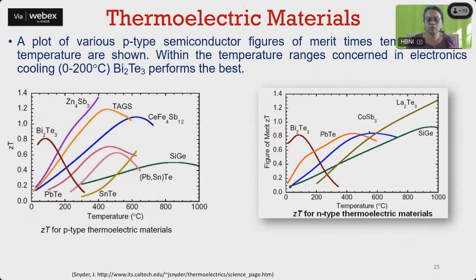Now these are a few of the elements. This is the p type and this is the n type. These are a few of the materials which are used. So you can see bismuth telluride performs the best in 0 to 200 degrees. This is the operating temperature in both cases. Working around 200 degrees, we see bismuth telluride, which is one of your topological insulators, it is also there. So this has a very good ZT.